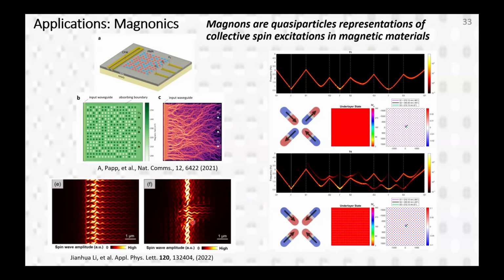This is also another artificial spin ice study where they put artificial spin ice on top of some magnetic thin film, and the artificial spin ice essentially acts as like a dipole field injection. So at the vertices of the artificial spin ice, the stray field will go into the magnetization of the thin film and change how the spin waves will travel through that magnetic thin film.